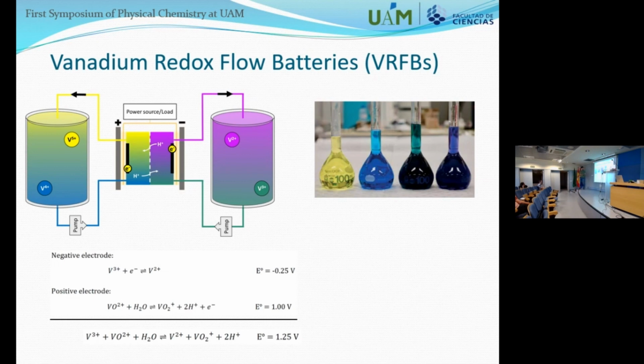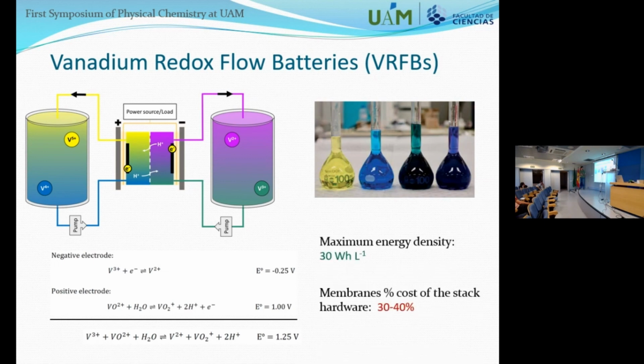The total voltage that we have is 1.25 volts, the standard potential of this reaction, and it allows us to store quite a good amount of energy in the material. The maximum energy density obtained nowadays with these batteries is around 30 watt-hours per liter, which is quite good, but still not as high as lithium batteries, which are approximately an order of magnitude higher. This is because of what we said, the difference between the liquid electrolyte and the condensed species in the positive or negative electrode of the other batteries.